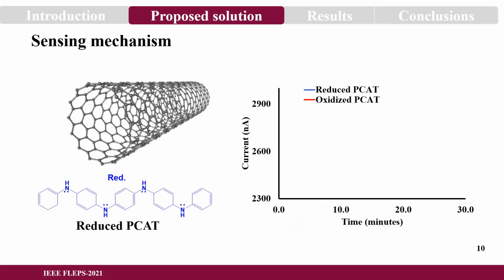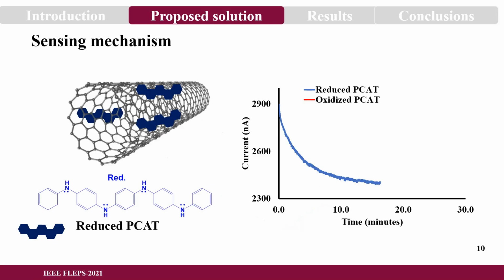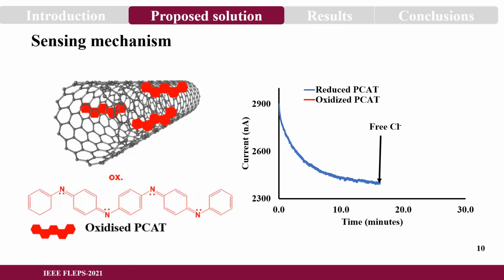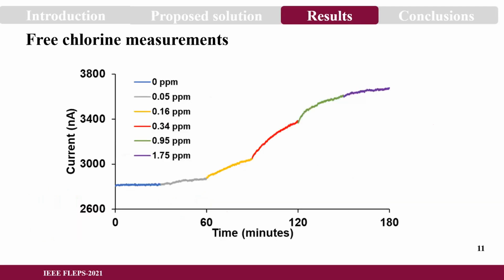The sensor works as follows. We load the sensor with an active molecule called PCAT, which makes it selective to species like free chlorine. When the sensor is loaded with PCAT, we typically see a reduction in current because of a reduction in the number of conductive pathways in the single-walled carbon nanotube network. Once we have free chlorine, due to the electron doping effect, reduced PCAT is converted to oxidized PCAT, and we see an increase in current, which is correlated with the amount of free chlorine present in the solution. As you can see, we have exposed the sensor to 5 different free chlorine concentrations, and the sensor saturated at the last concentration, but we can still measure the free chlorine concentration up to that point.